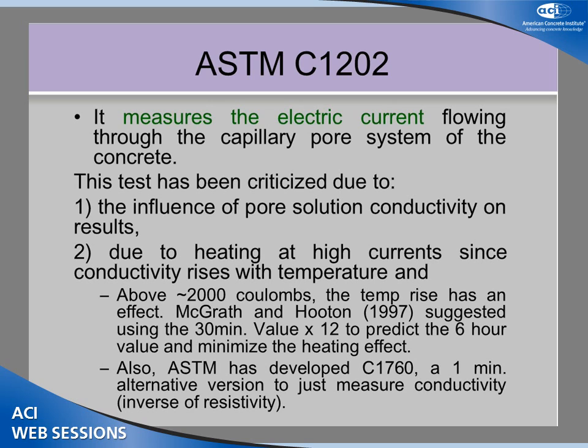And the analogy is you'll get more current flow through higher porosity systems, and systems with bigger pores and more connected pores, you're going to get higher current flow. If you have a more tortuous, fine pore network, you get less current flow.